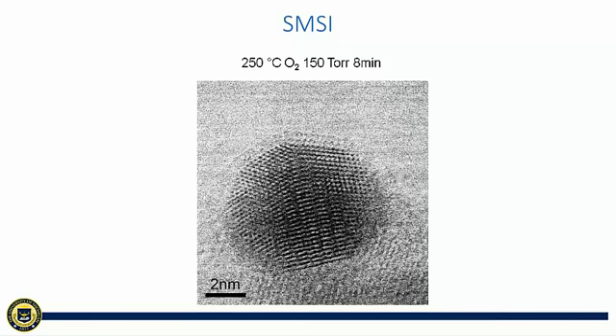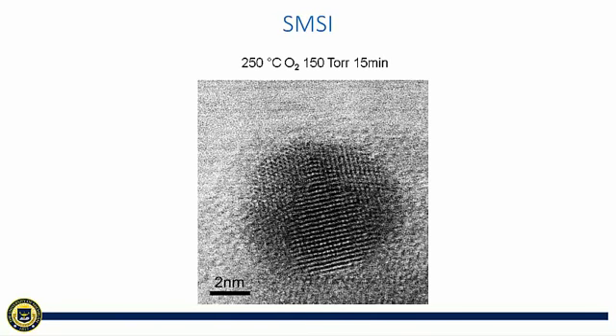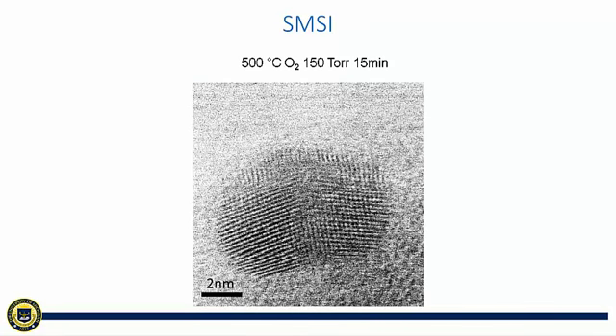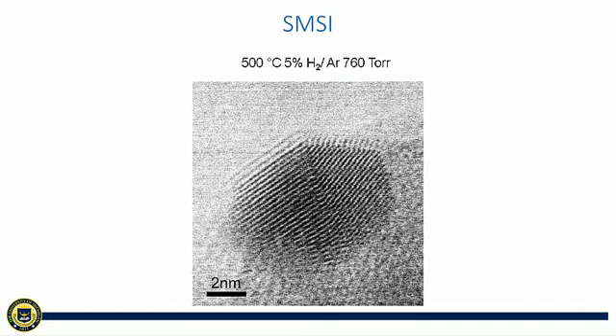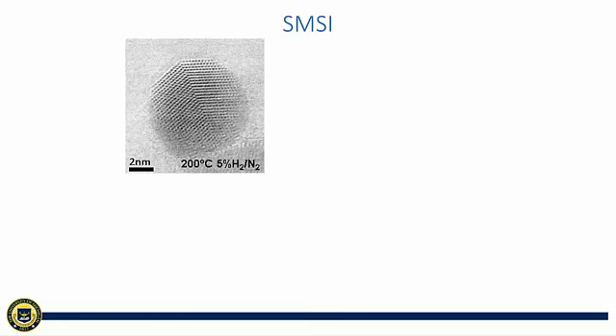If we change the atmosphere to oxygen, 150, which is comparable to the oxygen partial pressure in air, we can start to see the breaking up of the overlayer. And if we wait longer, it gradually dissociates. If we increase the temperature to 500 C, we can see it entirely dissociates. But if we change the gas to 5% hydrogen balanced with argon again, the crystalline bilayer reappears. So this process is reversible. And let's review it again.